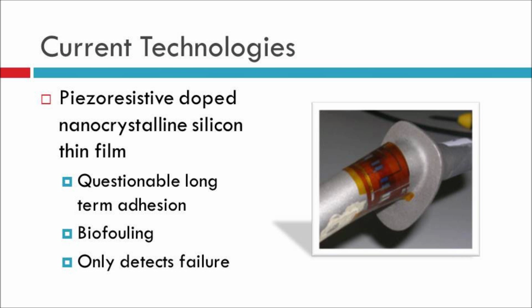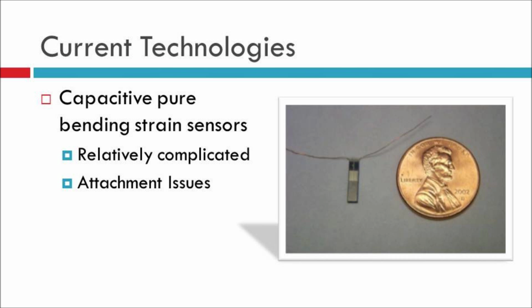As you can see in the picture, it's almost like a flexible circuit board that's wrapped around the base of the orthopedic implant. This particular design, however, is limited to the detection of only a catastrophic failure. There are also some concerns about biofouling or malfunction due to tissue interaction and its adherence longevity. Another group has designed a capacitive pure bending strain sensor for detecting stresses and strains of bone cement in spinal fusion applications. While this is a pretty good design, it's relatively complicated and may not be able to be attached to areas of interest for extended periods of time in the body.